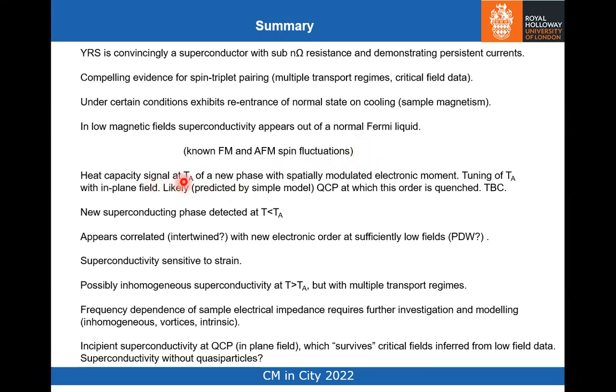We have a heat capacity signature at TA, in which we get a new phase with a spatially modulated electronic moment. We can tune that transition with in-plane field. And our simple thermodynamic model predicts that there is a quantum critical point at which this order is quenched, but we had to have measurements to confirm that. In low magnetic fields below that transition temperature, we see a new superconducting phase, SC4, which is identified with the diamagnetically screened phase seen by Schubert.